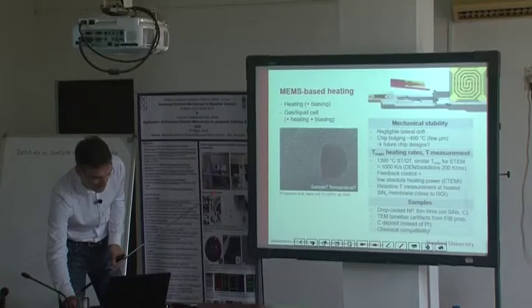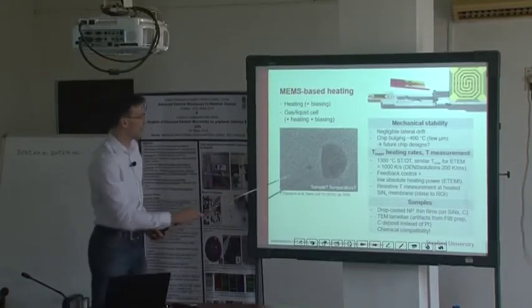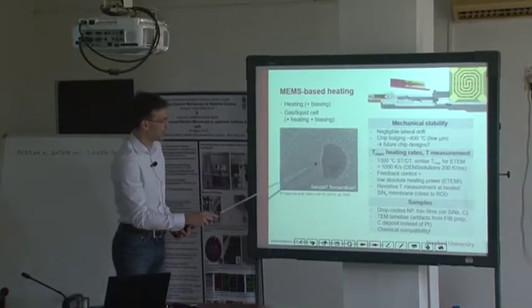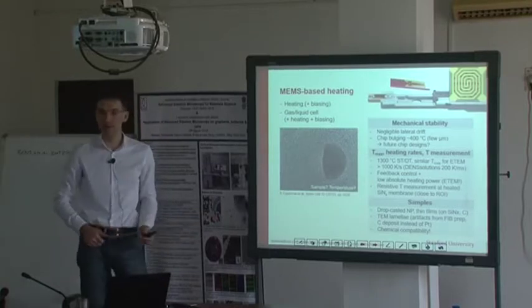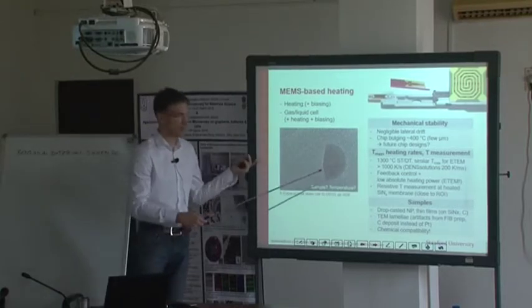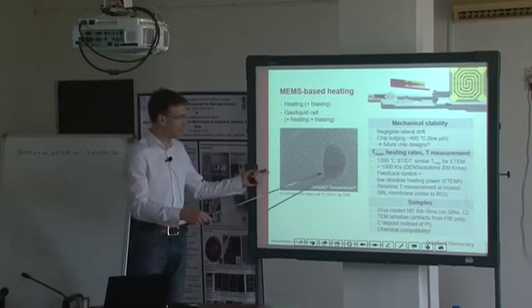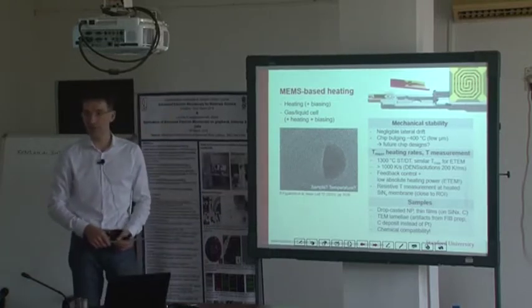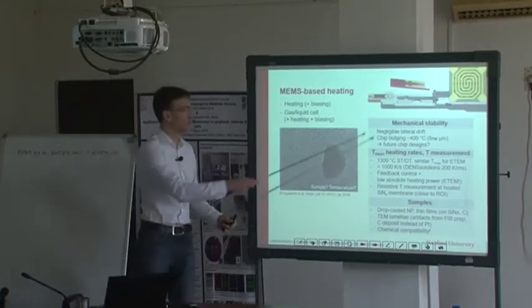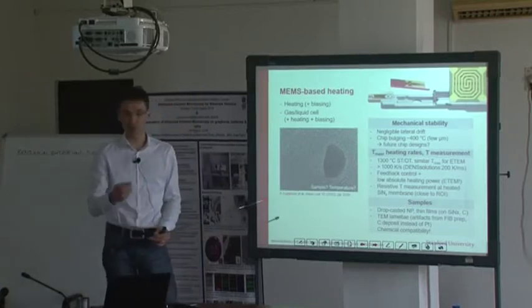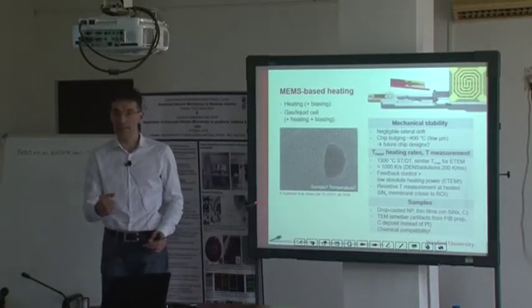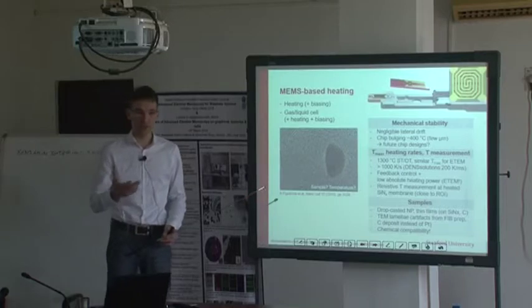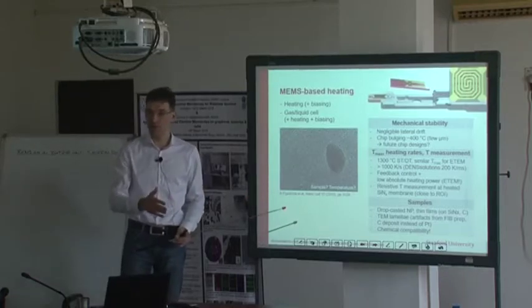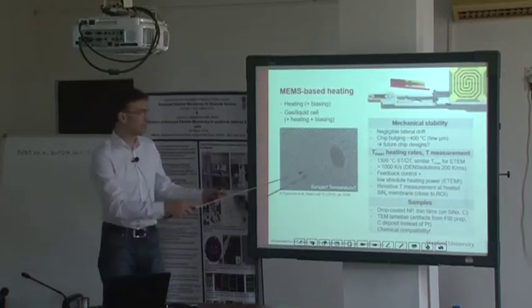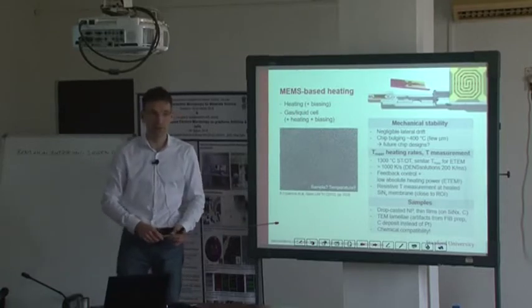On the left-hand side, there is another example of the recrystallization of a nanostructure here on the atomic scale. And you see that there is hardly any drift. So this is atomic resolution imaging. You get a static image. You don't have any drift of the sample. So this is the big advantage of using such MEMS-based heater chips, because you just heat on a very localized scale. The evolving heat and the evolving radiation at high temperatures is strongly reduced, so you can do EDS at temperatures far above 800 degrees Celsius.